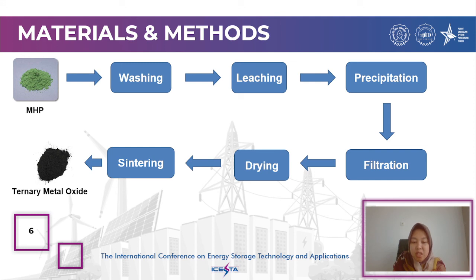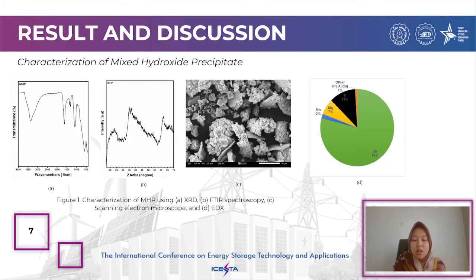The ternary transition metal oxide or NCM oxide was prepared by thermal decomposition of NCM oxalate precipitate at 500 degrees Celsius for 4 hours. To understand the characteristics of MHP, a series of characterizations was performed and the results are displayed in Figure